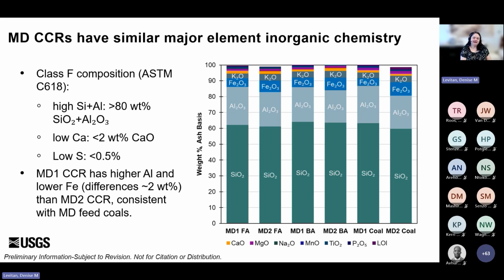There's some slight differences in the ratios between MD1 and MD2, and that's consistent with feed coals, which you see on the far right of this plot. Again, looking similar to the ashes, which is consistent with the principle that most of the chemistry of CCR is based on the coal that goes in. I guess that's a mass balance kind of approach. Also worth noting in these samples in particular is that they have really low sulfur in both the feed coals and in the CCR materials. And that means that at this CFB plant, at MD1, they add a minimal, if any, amount of limestone as an emissions control. That's different than a lot of CFB plants where they can add like a third of the amount of coal as the mass of limestone added. So it can be big, but here it's not.